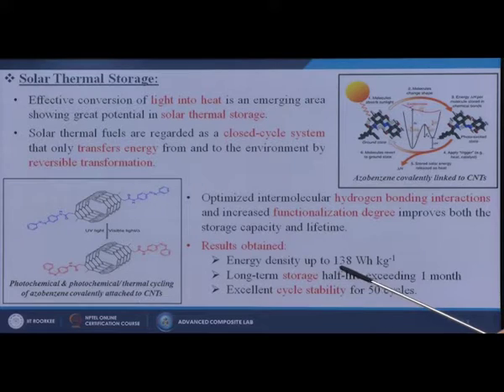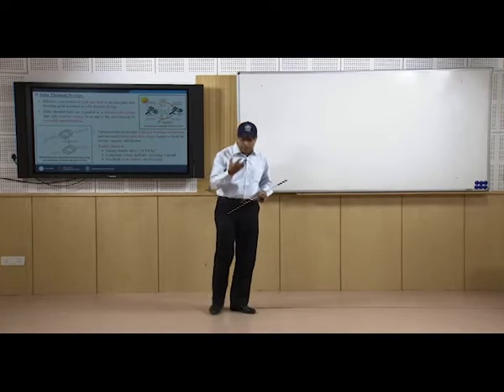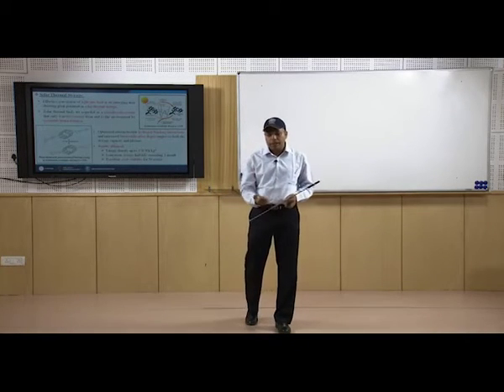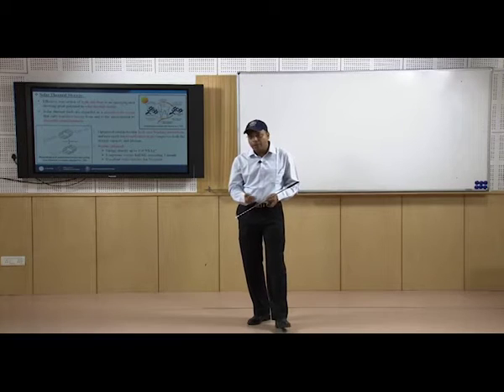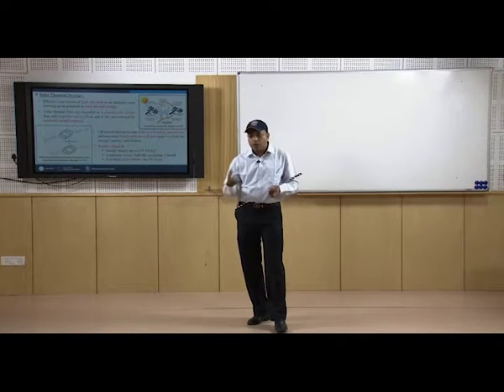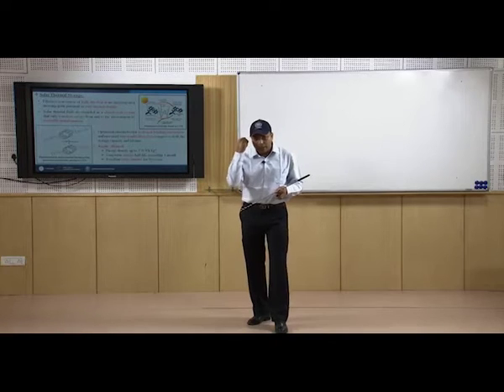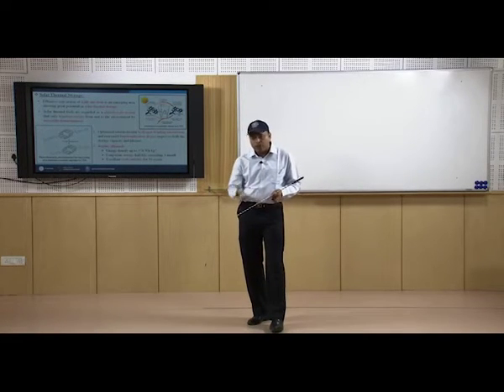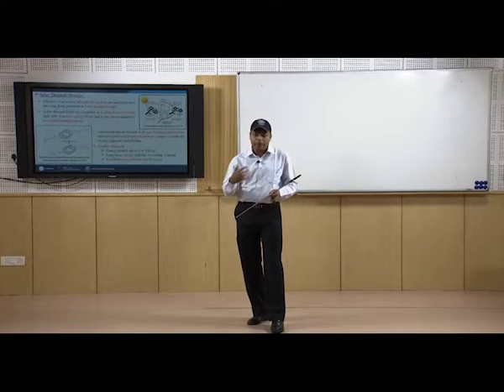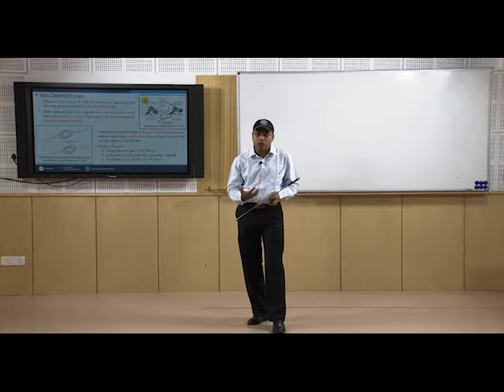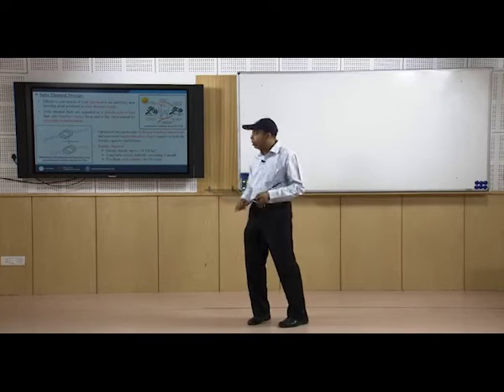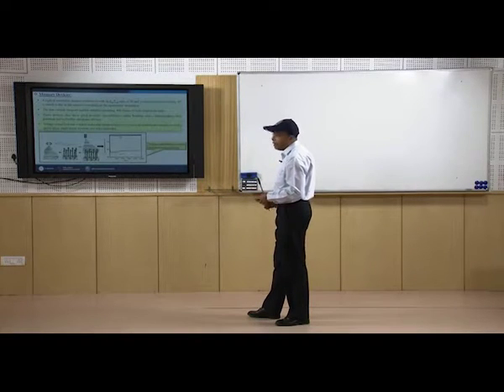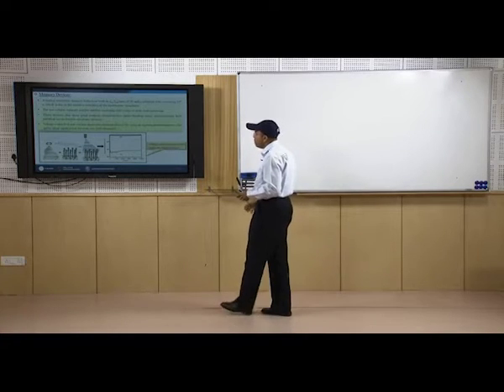Energy density up to 138 watt-hour per kg, long-term storage half-life exceeding 1 month, excellent cycle stability for 50 cycles. That means the stability of that particular material is increasing, so that I can use it for a longer time. Not only that, when I store energy in that material, the discharge time will also be increased. The material can store the same amount of energy for a longer time itself. Then we can use this kind of material for memory devices.